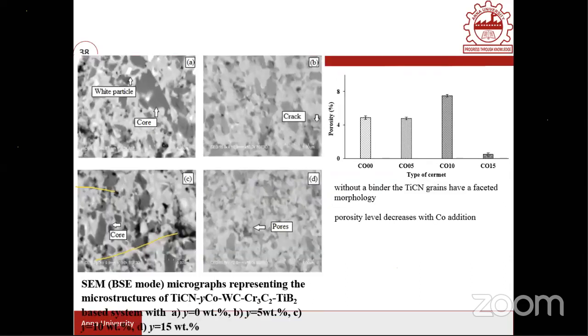And another case where you have cobalt, it's giving a really wonderful microstructure. Look at this. Comparing to other microstructures here, for probably 15% cobalt or 10% cobalt or even 5% cobalt addition, there is full densification, there is no porosity here. And also you can see the gray rim and, majorly, no, it is a white rim. That means it's the outer cover. And gray core. Gray core is basically TiCN based particle.